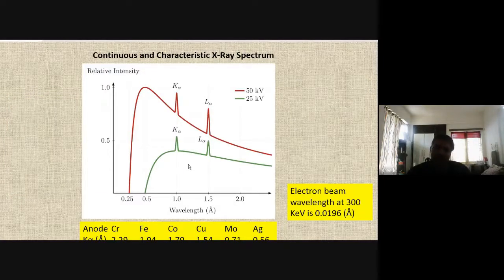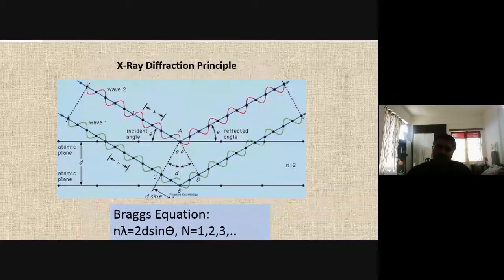So this is the graph of relative intensity with respect to the wavelength of characteristic X-ray, and it's a superimposition of continuous X-ray and characteristic X-ray. And these are the K alpha wavelengths of different materials used for X-ray diffraction. See, chromium 2.29 angstrom, iron 1.94 angstrom, and copper 1.54 angstroms, which is commonly used for X-ray diffraction techniques. And you have the electron beam wavelength, for comparison, where the electron beam in SEM and TEM is used as the source of characterization, with a wavelength of 0.0196 angstrom. So you have the X-ray, and the X-ray comes in contact with one of the atomic planes, and it reflects back at a particular angle.